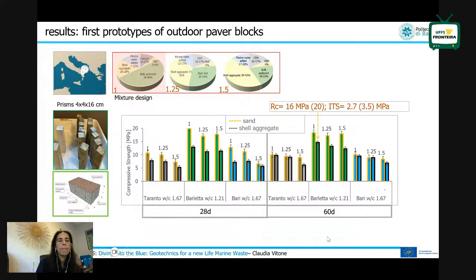As you can see here, in this plot we have compressive strength. We have different sediments. So in blue, the sediment from Bari; in green, the sediments from Barletta Port, which is essentially a sand, and the Taranto material. The Taranto material is a silty clay. The Barletta sediment is a clay sand, and the Bari sediment is essentially a silty clay. So totally different materials, three different sediments in their natural state.